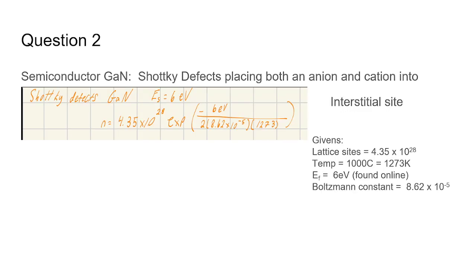And then to find the Schottky defects, it's the same formula but just a different activation energy. So that's represented by 6 eV. So we would input 4.35 times 10 to the 28 lattice sites times exponential negative 6 eV divided by 2 Boltzmann constant and temperature of 1273 Kelvin.